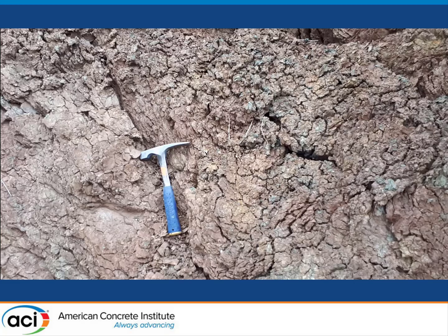Some of these clays are so pure, monomineralized smectite, that they are sold as bentonites. Other clays contain a little bit more kaolinite, a little bit more illite, and we have some horizons with limestone, more marly horizons. But the big thing with this is, of course, that it's so pure and it's fairly widespread.